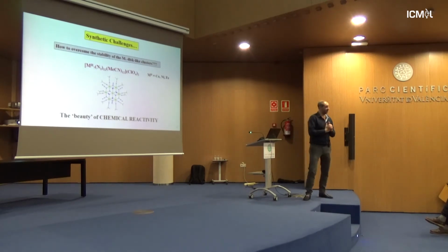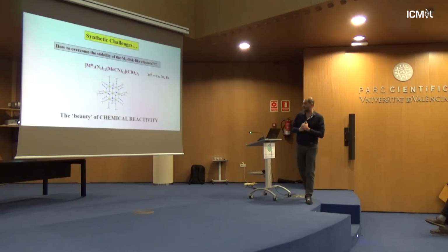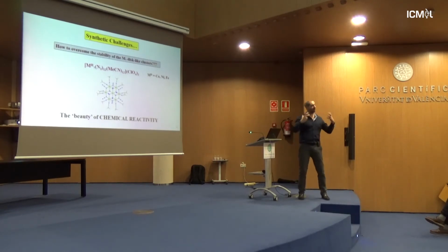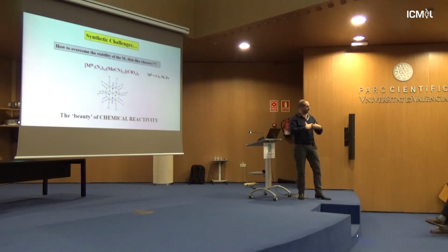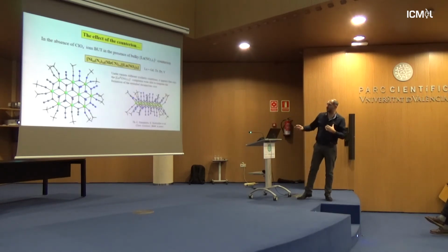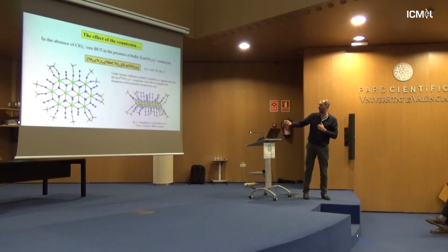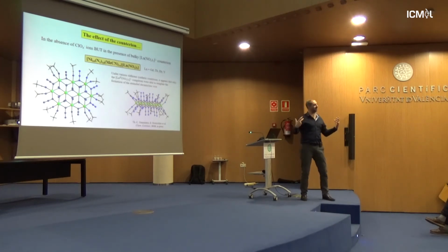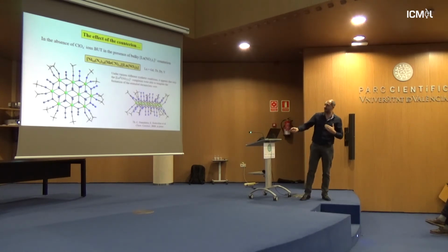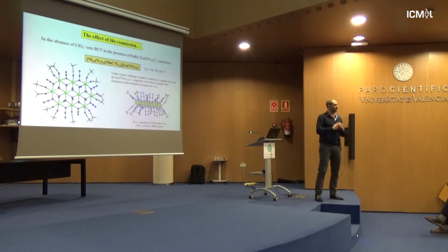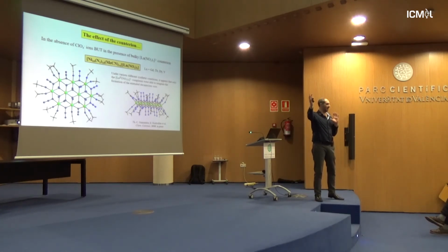So I asked my student, in collaboration with German partners, due to the Humboldt fellowship that I have, to try and replace those perchlorates with larger or smaller counterions. And we figured out that when you use lanthanide nitrate salts, the very common lanthanide nitrate counterion, you are able to template the formation of 2 fused heptanuclear units and get a new class of decanuclear nickel-10 compounds, again with that beautiful layer structure here, and the lanthanide nitrates are just acting as counterions.